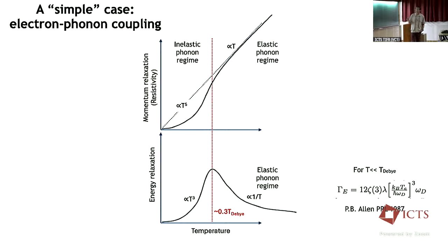This regime up here we would call the elastic phonon regime. It comes about when the electrons involved are thermally excited with enough energy that they have energy a lot larger than the characteristic phonon energy. And so it looks basically like elastic scattering, or scattering off of impurities, because, again, the electrons have so much more energy. The energy relaxation in the same scheme is quite interesting. At the lowest temperatures, it would go like T to the 3rd.